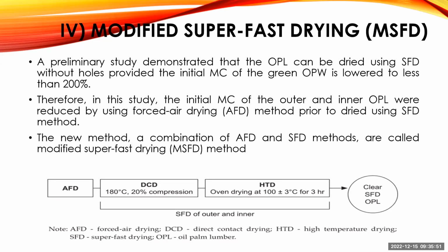A preliminary study demonstrated that oil palm lumber can be dried using super fast drying without holes, provided the initial moisture content of the green oil palm wood is lower than 200%. Therefore, in this study, the initial moisture content of the outer and inner oil palm lumber were reduced using the forced air drying method prior to drying using the super fast drying method.